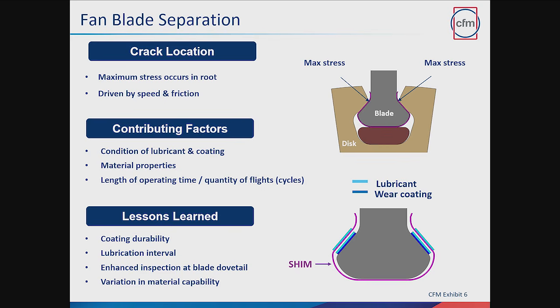Okay, so from the causes and contributors, let me try to explain where we got to during the investigation. So when we designed the 7B fan blade system, we designed it to have a lower contact pressure between the blade dovetail and the disc dovetail contact surfaces, which you can see up on the upper right chart. When we got the results from early engines, what we call EIS or entry into service, some of those early engines, when we looked at the fan blades, it indicated the coating system was not staying intact as well as we had anticipated with the design change.